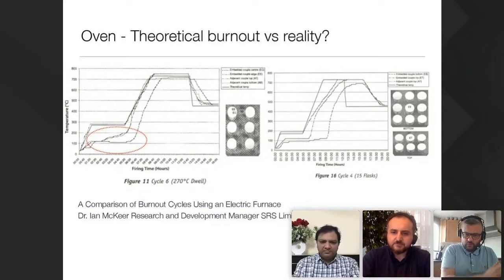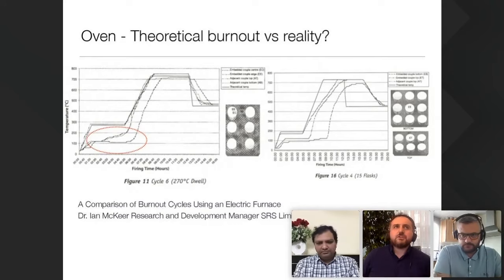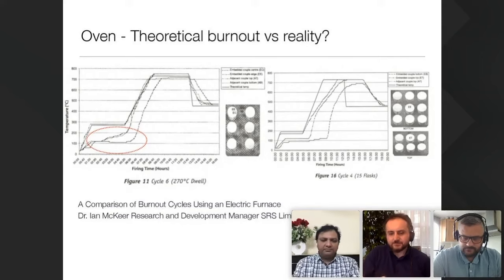If they've set it to 600, you need to wait. As soon as the digital readout reads 600, it doesn't mean the core of the flask is at 600 degrees. The core of the flask may still be at 700, 720. That's why we wait a minimum of 1 hour, so that slowly the heat goes down. Because at the end, what matters is the inside of the flask, because that's where your metal is going to enter.